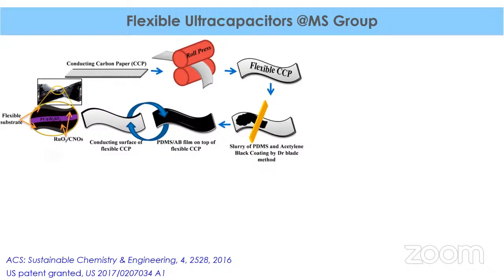In this process, the conducting carbon paper, which is composed of carbon fibers, loses its brittleness and becomes flexible. Then he coated it with a fine mixture of PDMS. PDMS is a kind of elastomer, polydimethylsiloxane. He mixed it with acetylene black, because PDMS is not conducting, to make it conducting, and coated it on one side of this flexible carbon paper to hold it, because if we roll-press this carbon paper, it becomes difficult to hold. It can break apart also. So he coated this elastomer on one side to give it flexibility as well as sturdiness.